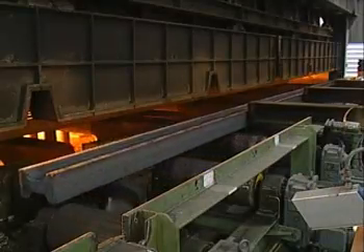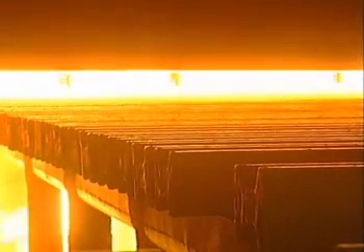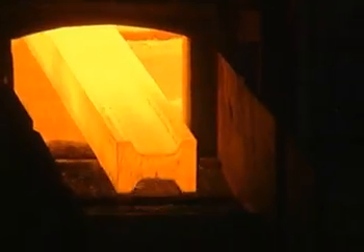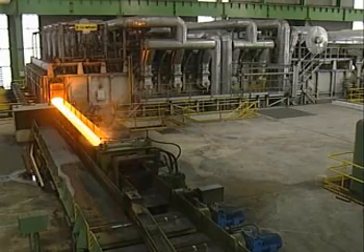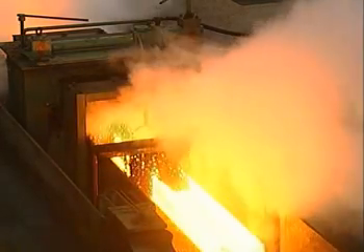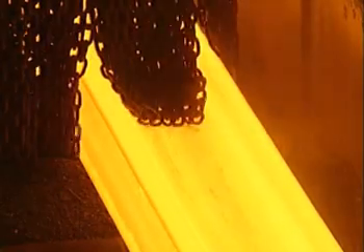The starting material is charged into the walking beam furnace for heating. Furnace capacity is 175 metric tonnes per hour. It leaves the furnace at a homogeneous discharging temperature of 1,250 degrees Celsius and is fed to the mill train. Descaling is performed with high pressure spray water on the way to the roughing stand.